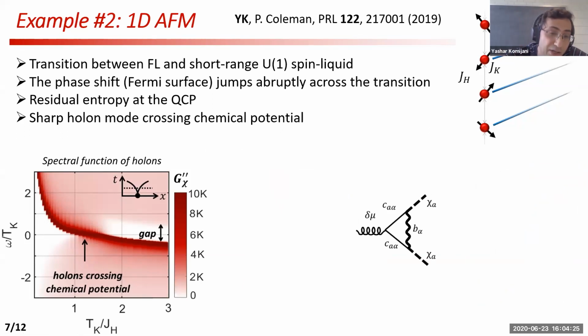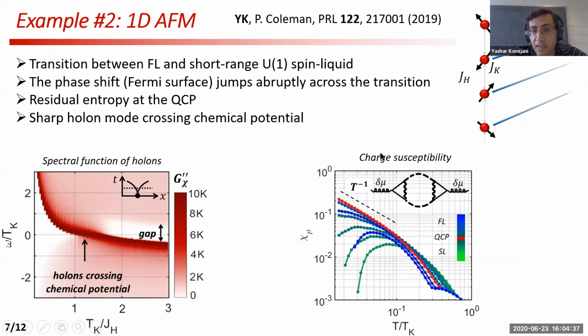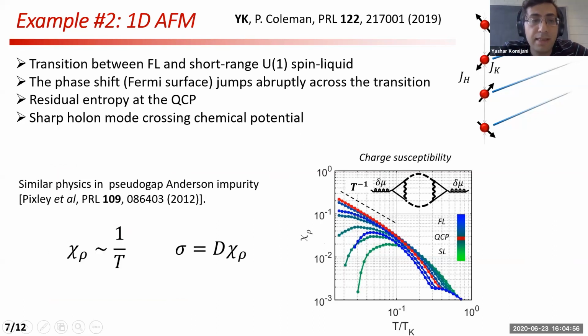Since the holons are critical and they are charged, it can be shown that they do contribute to the charge fluctuations. If we compute the charge susceptibility, the conduction electrons contribute, the holons contribute, and in fact we get a divergent charge susceptibility at the quantum critical point. So this is the transition between the Fermi liquid, going through the critical point, to the spin liquid, and right here is 1/T. And this sort of critical charge fluctuation at the Kondo breakdown has been seen in pseudogap Anderson impurity systems, but never on a Kondo lattice before.